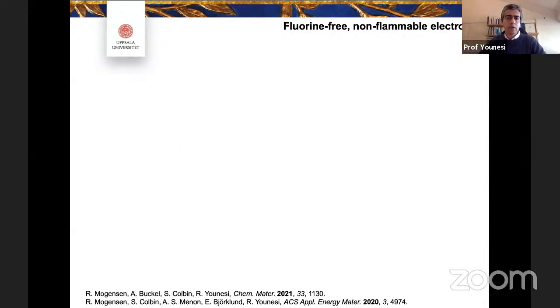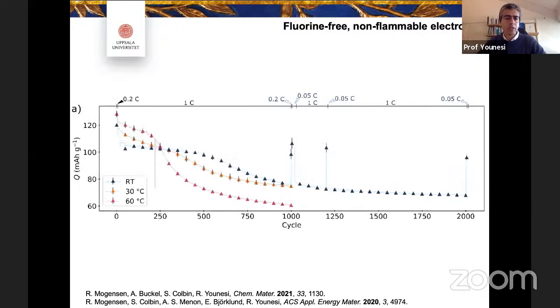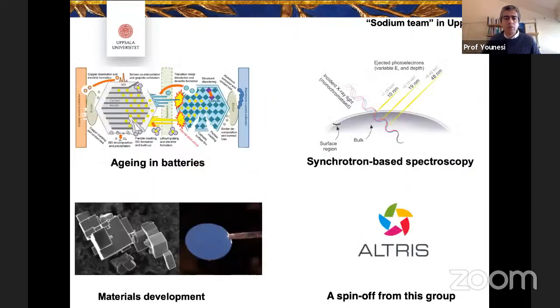And very recently, we have demonstrated that with such electrolyte in full cell sodium-ion batteries with Prussian white cathode, we can cycle the battery up to 2000 cycles. There is definitely some capacity fading. So we are reaching 50% of the initial capacity after 2000 cycles when we cycle at room temperature. And this is something for us to understand and work more on. And that is why we go to synchrotron-based measurements and a number of different spectroscopy measurements to understand what the aging in sodium-ion batteries is and how we can suppress aging.